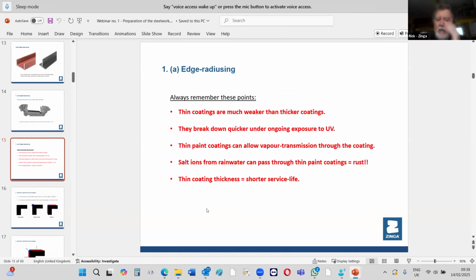So these are the points. Thin coatings are always weaker than thick coatings. This also goes for paints as well. They will break down much quicker under UV. And also, as I said earlier, thin coatings can allow vapor transmission. So actually, your overnight condensation sitting on the paint can penetrate at a microscopic level. It can go through the paint onto the steel, believe it or not. So if you apply it too thin, that actually harms it. And the same goes for rainwater.